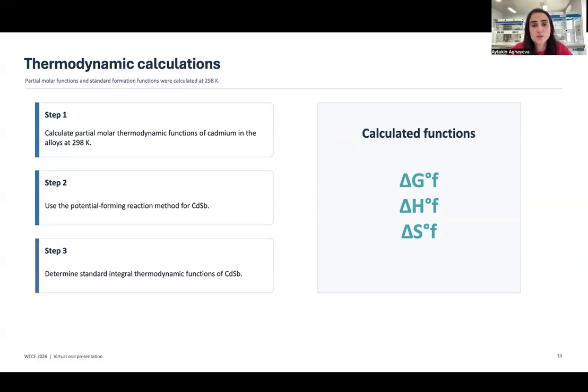The thermodynamic calculations were carried out in several steps. First, the partial molar thermodynamic functions of CdSb alloys were calculated at 298 Kelvin. Then the potential forming reaction method was used for CdSb. Finally, the standard integral thermodynamic functions of CdSb were determined. The calculated functions include standard Gibbs free energy of formation, standard enthalpy of formation, and standard entropy of formation. These functions are important because they characterize the stability of CdSb and can be used for comparison with literature data.